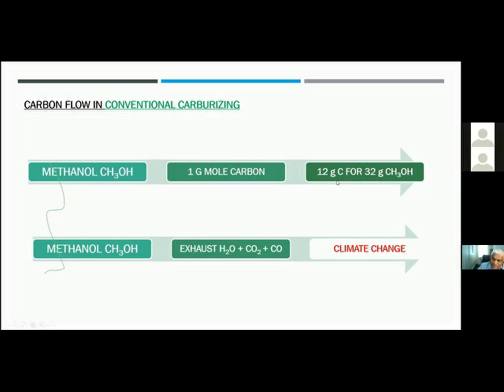Today's carburizing is 36% inherent. So you can imagine the amount of methanol you need to pass. It's inherently designed to pass 4 times, 5 times more methanol. And since methanol is not passed alone, it's passed with nitrogen. Or you need to compensate it through endogas, which is a mixture. So when you pass methanol or endogases, you're going to end up getting exhaust. And the exhaust will, of course, be H2O because it has got hydrogen. Of course, it's going to be carbon because you're passing excess methanol. So it's going to be CO2 and CO.